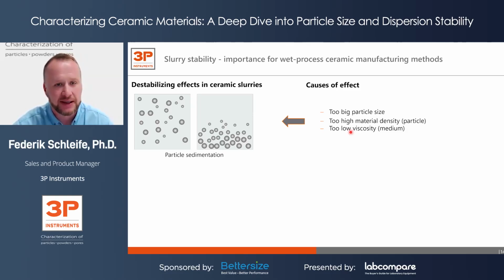So you can imagine that those ceramic particles might pretty fast start to settle down, to sedimentate in a liquid phase. Therefore, if the particle size is too high, you get a really fast sedimentation, so a smaller particle size would prevent sedimentation of the particles for a longer time. Also, if the material density of the particles is very high compared to the medium of water, or the viscosity of the medium is pretty low, you might also get really fast sedimentation.